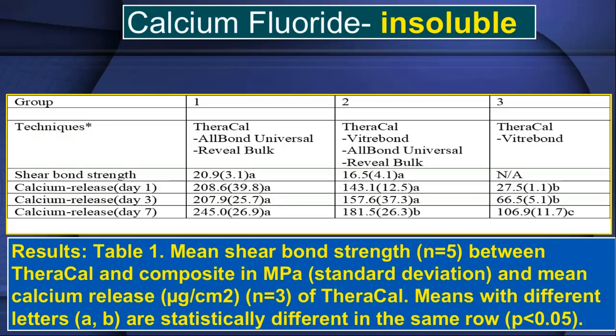It's pretty significant. But you have a big, huge increase in the calcium release as opposed to what happens when you do the Vitrebond. The Vitrebond greatly reduces the calcium. And you notice the Vitrebond because if you take the Reveal off the top of the Vitrebond, it reduces it even more. And so what happens is when you look using your calcium electrode and look in the solution for calcium, you just won't find it because it's now calcium fluoride.